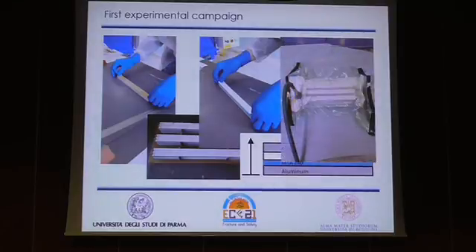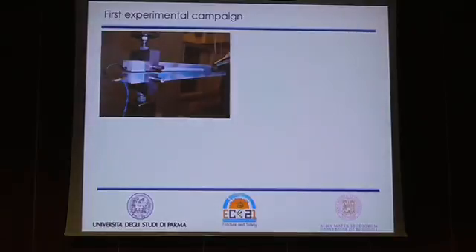The bonding template went into a vacuum bag, which underwent a 1 hour curing cycle in autoclave at a temperature of 120 Celsius degrees and a pressure of 2.1 bar. DCB tests were performed according to the international standard ASTM D3433 in displacement control at a constant crosshead rate, and the values of the crack opening displacement were measured by using an omega clip gauge. In order to obtain a crack with a sharp tip not artificially created, a fatigue pre-cracking phase was performed until the crack propagated for 5 millimeters.